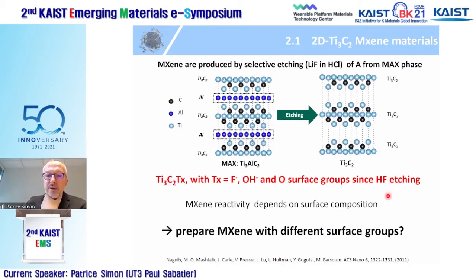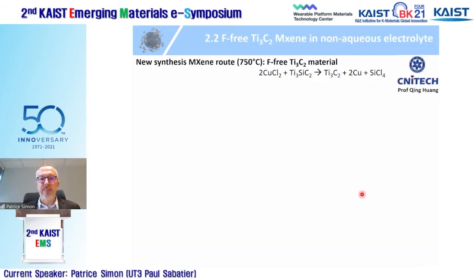However, these materials are mainly produced from fluorine-containing etching, electrolyte etching. And we know that MXene reactivity depends on the surface composition. So the question is, is it possible to prepare MXenes with different surface groups? In other words, is there a way to develop a new synthesis method that you can use to tune the surface chemistry of MXene?